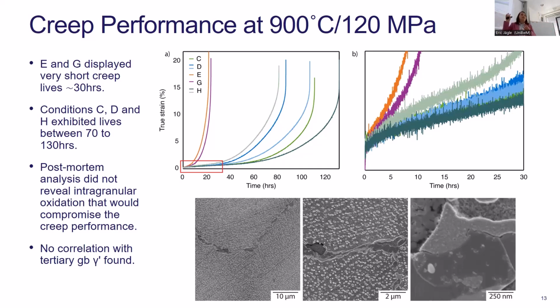So even with a 30% issue, we wouldn't get much higher than that, or even close to what we were looking at. And the post-mortem analysis that we did on the fracture surfaces didn't actually show any oxidation to suggest that that was the reason why we were getting the bad creep performance. And there wasn't any correlation in the end with the tertiary gamma prime at the grain boundaries.